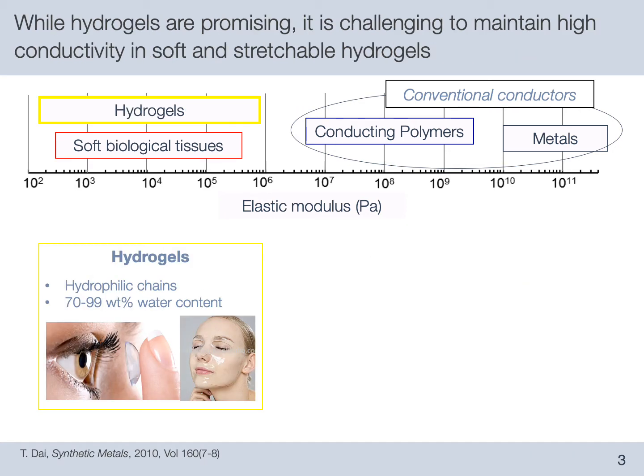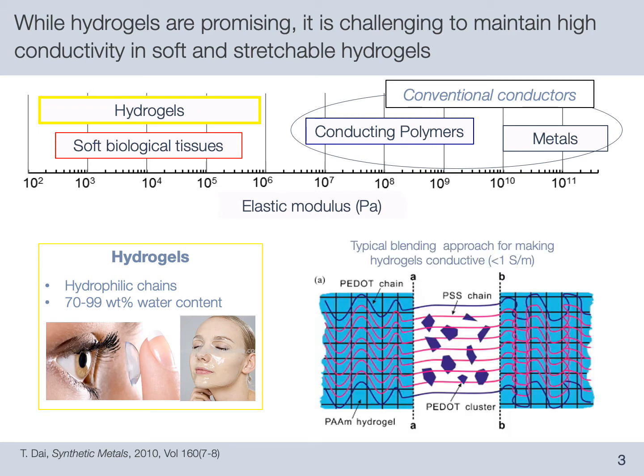To overcome this mismatch, hydrogels are a promising class of polymeric materials that possess elastic moduli comparable to soft tissues because of their high water content. Unfortunately, prior attempts to make hydrogels electrically conductive typically involved blending stiff conductive fillers into a soft and stretchable hydrogel matrix. This approach inherently results in a trade-off between conductivity and softness, so that gels that actually possess desired mechanical properties typically have very low conductivities of less than 1 Siemens per meter.